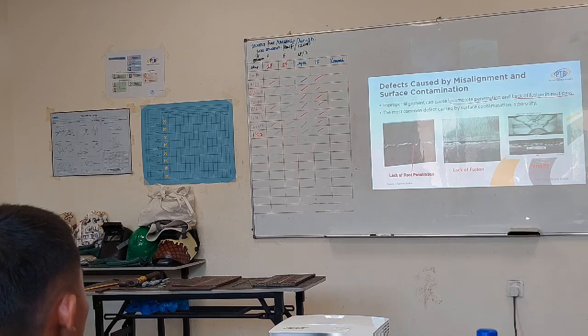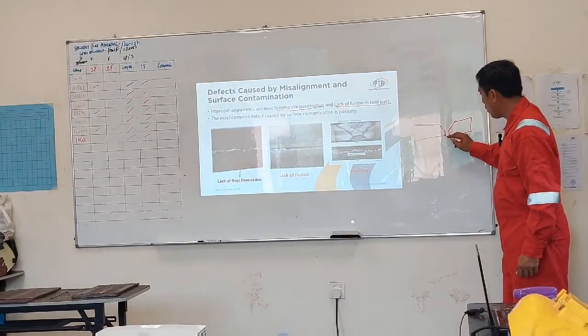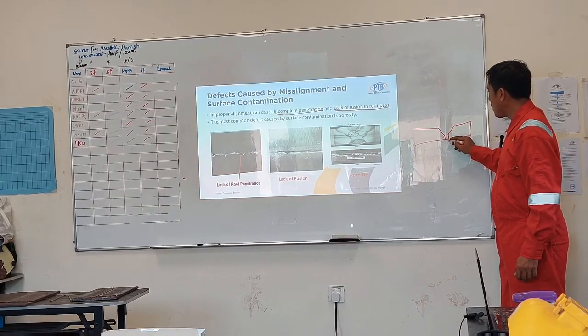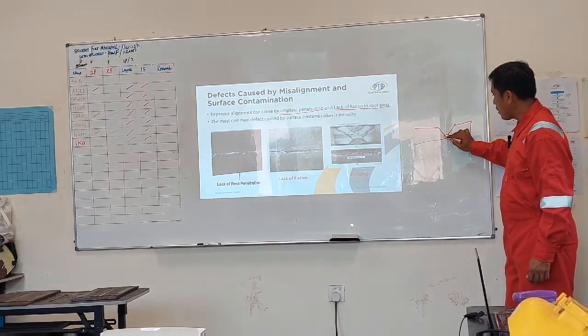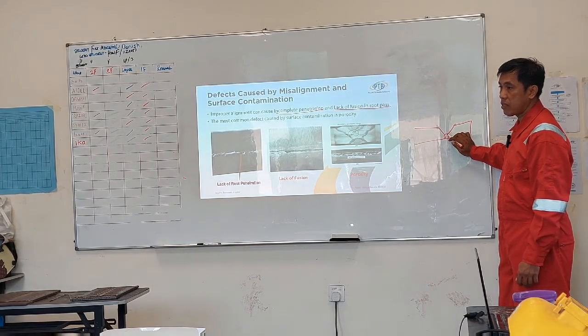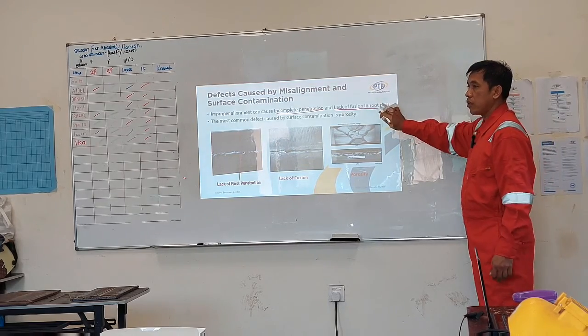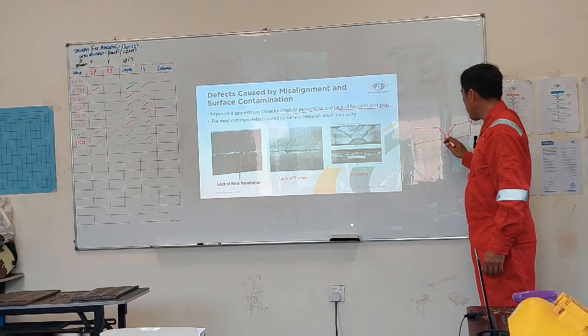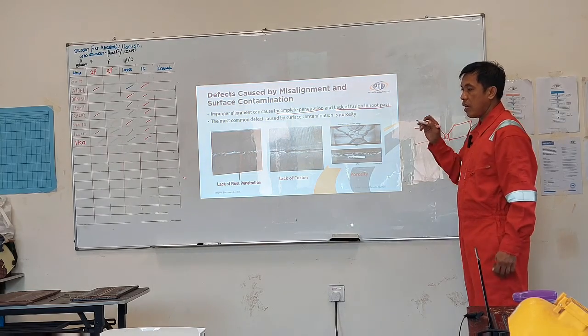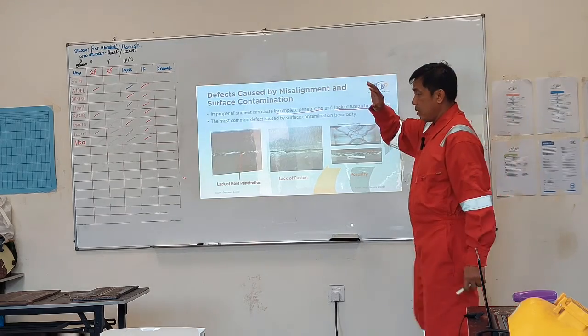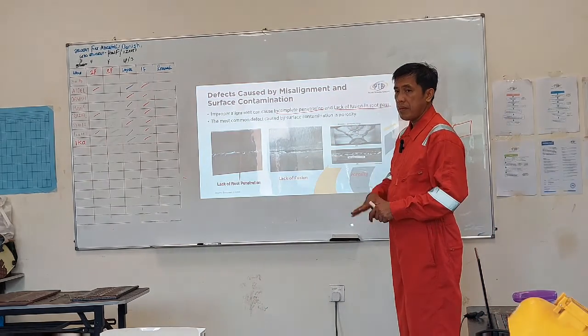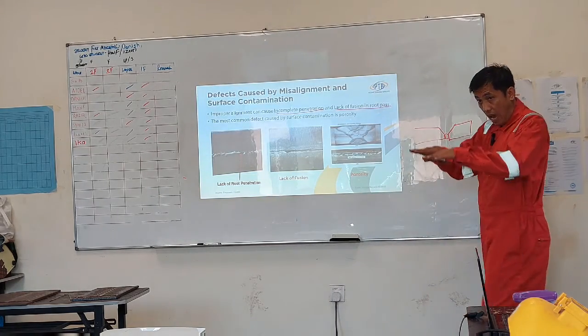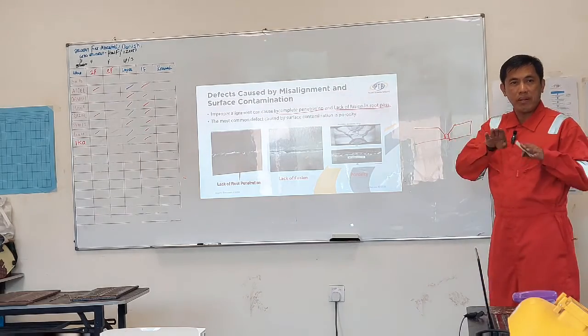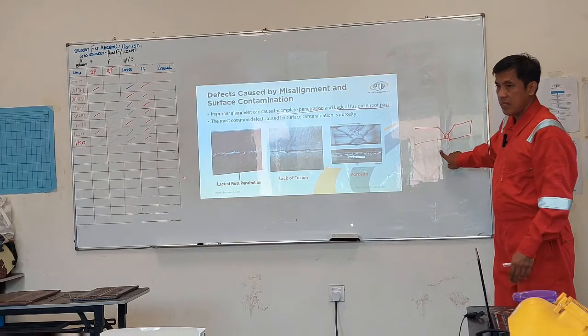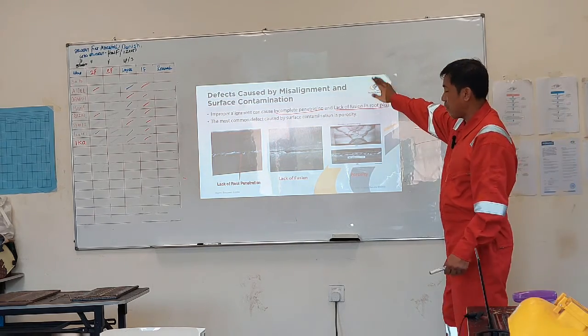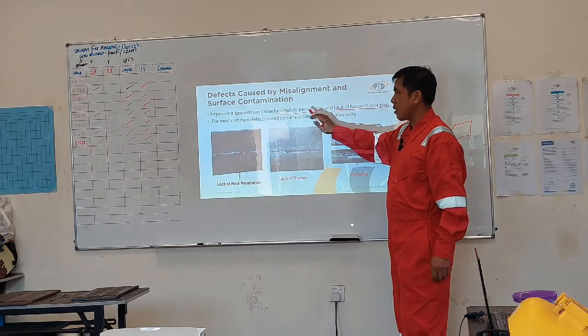Okay, this is high-low. So, when you start welding, most of the problem is only one side is melting, the other side is not melting. So, this is what we call lack of fusion. You see, one side is melting, the other side is not. This is the defect that usually happens if your plate is misaligned or high-low. That's why, if you remember, we always check the alignment. The welder usually has problems if the plate is not aligned. That's why the alignment is very important.